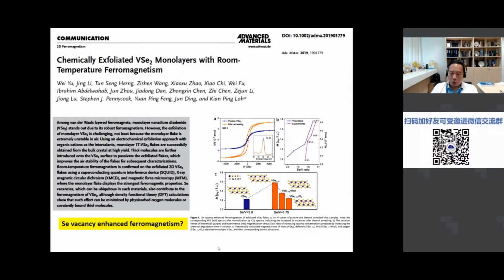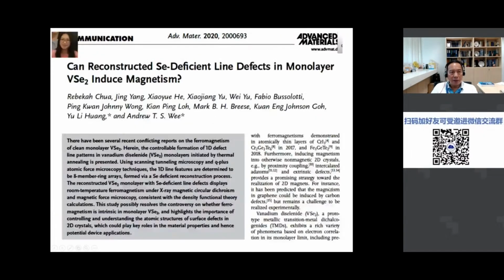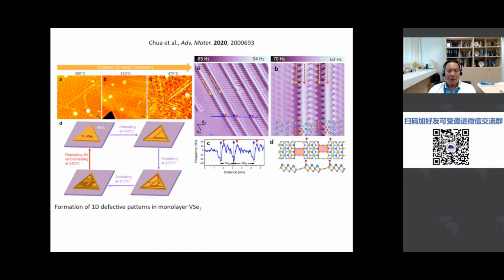Okay, so that brings us to the paper by Rebecca. She's writing up a thesis now. So her paper directly questions whether selenium deficient defects can induce magnetism. In this case, the defects we were working on were line defects. If you look at the figure on the left, you will see that initially the vanadium diselenide has a low density of line defects.